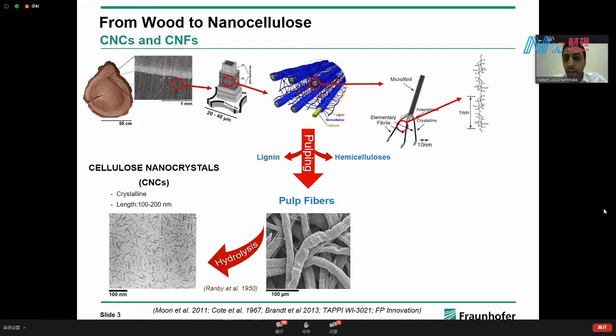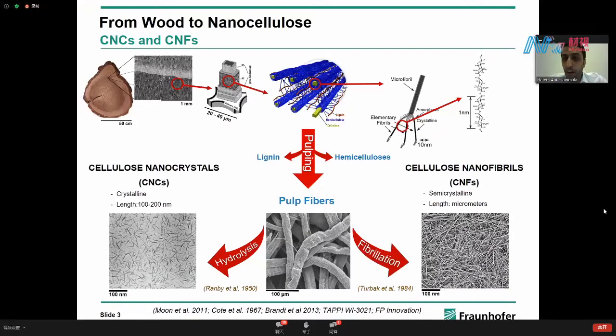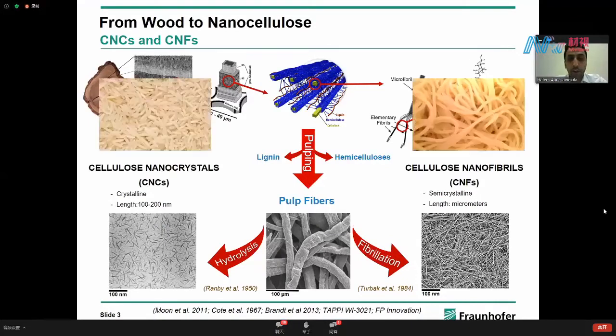The other form of nanocellulose is cellulose nanofibrils, and these fibrils are semi-crystalline, spaghetti-like nanoparticles with a thickness of a few nanometers up to tens of nanometers and a length in the micrometers. These cellulose nanofibrils are produced by mechanical fibrillation of pulp fibers. In general, no chemicals are used in such processes, or at least small amounts. So if you can't remember the names, you can remember them as rice-like nanoparticles or spaghetti-like nanoparticles.